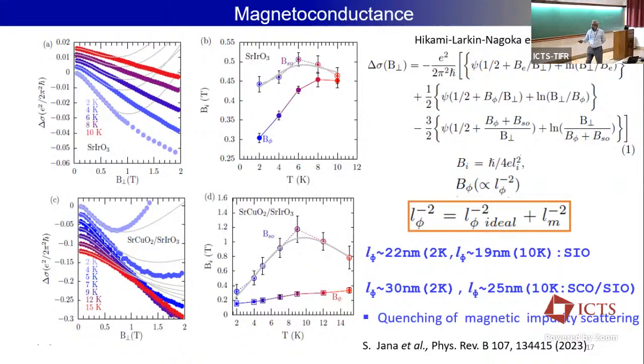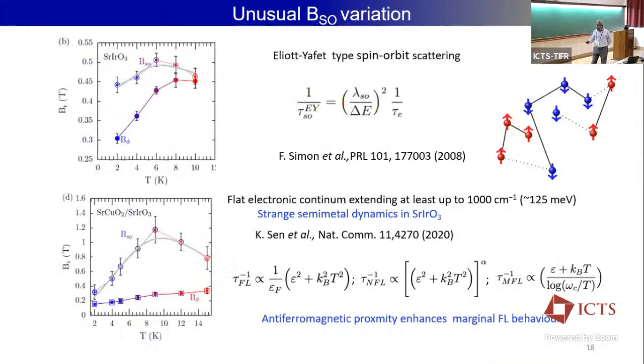But if you look at the BSO for both, BSO typically does not show a temperature variation. But what we see is a variation of BSO with temperature, and this was kind of intriguing, a large variation of BSO for the bilayer, where your SrIrO3 is grown on SrCuO2. So we wanted to try to understand what could be the mechanism.